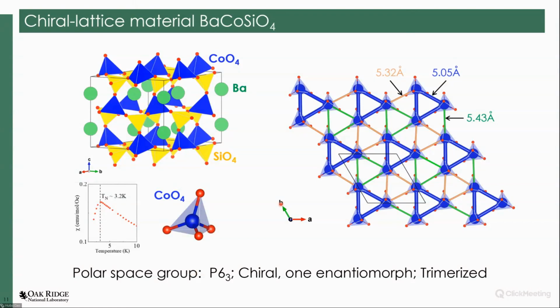Another thing is, if you look down from the c-axis, the symmetry is P63, chiral, also a polar space group. So it's a structure where, as we solved by structure solution, we know there is only one enantiomer. That means only one chirality, so we don't have a twin. That's actually universal for most cases. Only one chirality exists, like DNA. In many cases there is only one enantiomer.